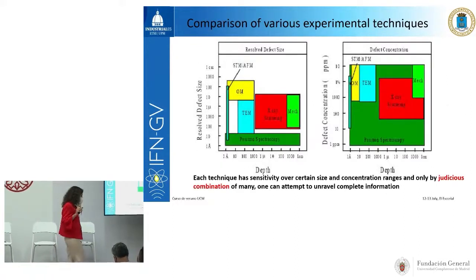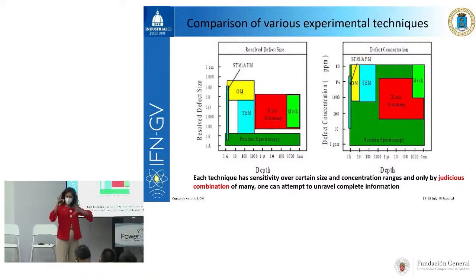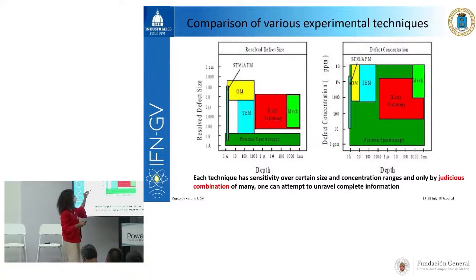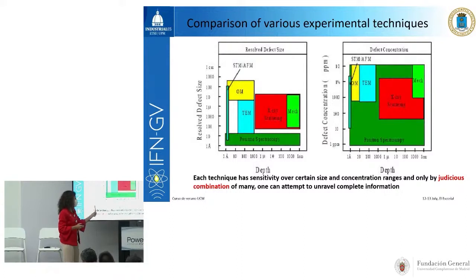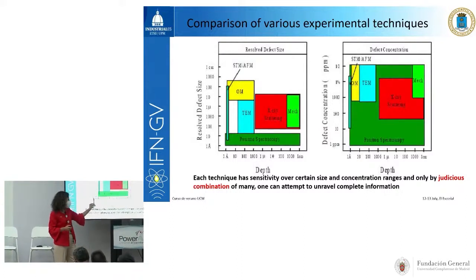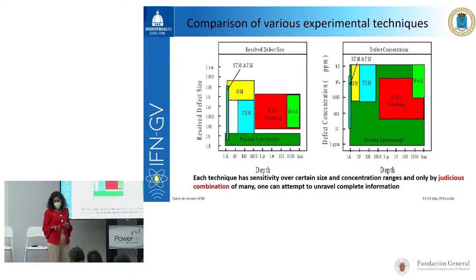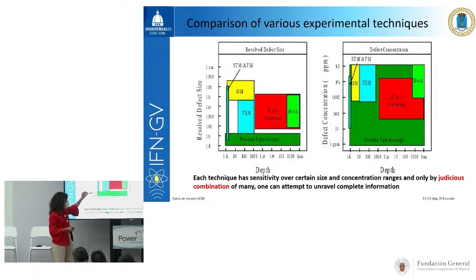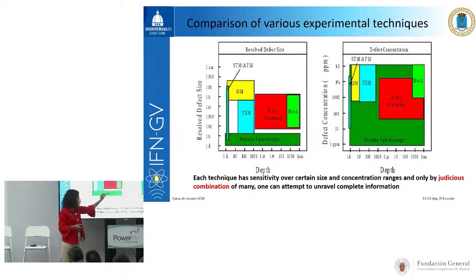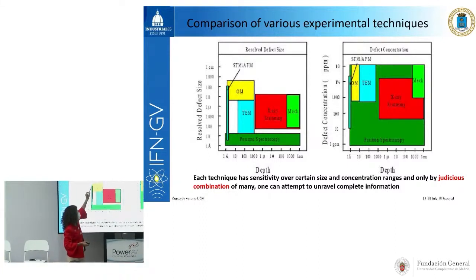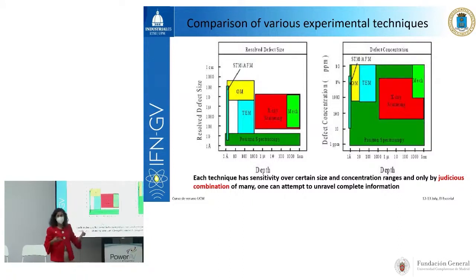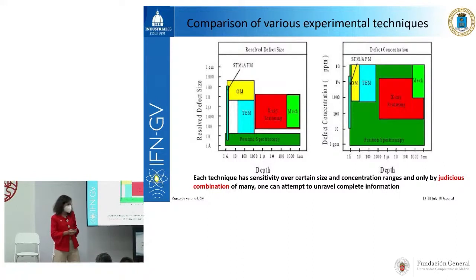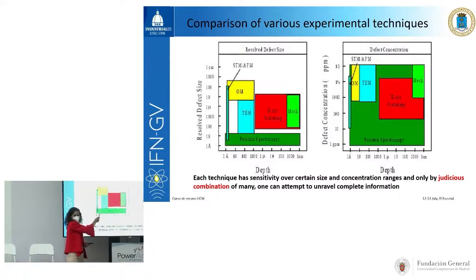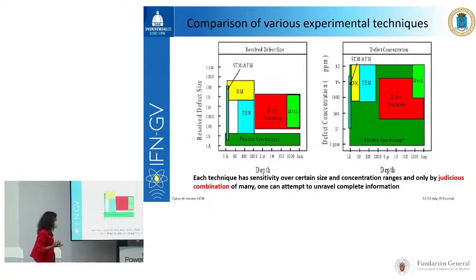This is only a picture to show you how we match the different techniques depending on the answer we expect. Here you may see the defect sizes we have, and here you may see the depth in the sample. This will be the sample surface, and this will be the distance underneath the sample surface. If we want to identify very small defects, between 1, 2 and 10 angstroms, we make use of positron spectroscopy. On the contrary, if we want to identify very large defects, in the micrometer range or even below, then we go to optical microscopy. So if we have to choose a technique to observe these defects, we are not going to use positron spectroscopy, because optical microscopy is going to give us the answer we are looking for.